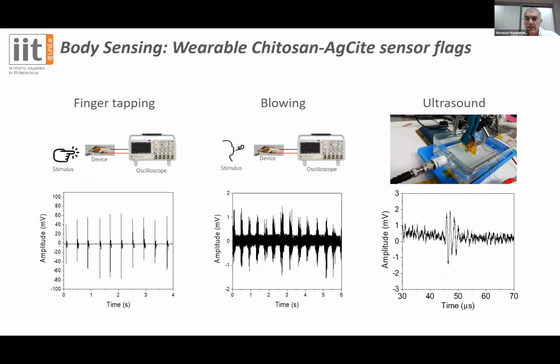So we tested this sensor in order to see its ability in detecting stimuli such as pressure and force. In this case, we used the sensor in a finger tapping test by gently touching the sensor with fingers, or we tested the sensor as a flow sensor by blowing and seeing the output response of the sensor. But we also tested this sensor for ultrasound applications as a receiver, as a detector for an incoming wave in liquid, in this case in water.